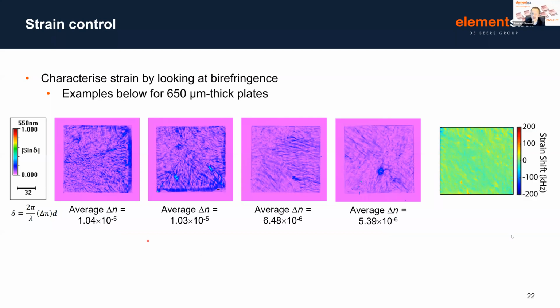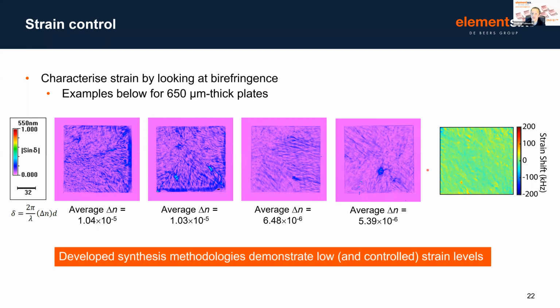But what is particularly nice is our collaborators, again at Harvard University, the Walsworth group, have actually developed new techniques to use the NV centers in diamond themselves to actually map out the strain and the shift in the resonance lines of the NV centers that's induced through the presence of strain. That's the map that I illustrate here. And the strain shifts that they found are well below the line width that you will observe for this sort of NV center concentration. So it's another way of saying that the presence and level of strain in this material is by no way at a level high enough to detrimentally affect the coherence time in this material. So hopefully the message that I've got across here is the developed synthesis methodologies have demonstrated low and controllable strain levels.